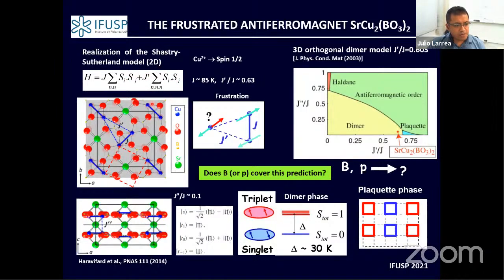The exact solution of this Hamiltonian brings a different basis of eigenstates related to spin, where the ground state is a singlet state with spins in the dimer antiparallel, characterized by an energy gap separating the spin singlet state with total spin 0 from the excited state with total spin equal to 1. This gap is determined by theory to be on the order of 30 Kelvin, also confirmed by experiment.